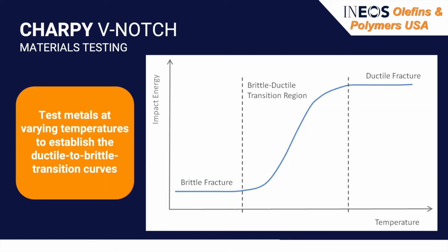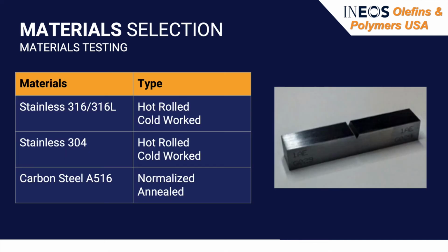In addition to the design solution just discussed, the team conducted Charpy V-notch experimentation to determine if replacing pressure vessel DD308 with a different metal would prevent brittle fracture. Charpy V-notch testing consists of dropping a hammer onto metal samples and measuring the impact energy. By testing at varying temperatures, a brittle to ductile transition curve for a metal can be developed. The goal was to find a metal with a ductile to brittle transition temperature colder than the current pressure vessel. The team tested 3 different metals, each at 2 different heat treatments. The current material of pressure vessel DD308 is A516 carbon steel normalized.